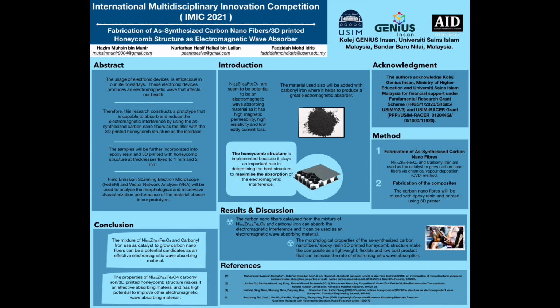So for the method part, it is divided into two phases. The first one is fabrication of synthesized carbon nanofibers. Nickel zinc ferrite nanopowder will be produced by using high energy ball milling apparatus. The milled powders then will be sintered at 900 degrees Celsius for 10 hours. The nickel zinc ferrite will be further mixed with carbonyl iron and used as catalyst to grow carbon nanofibers. An ethanol solution is used as the carbon source to grow the carbon nanofibers by chemical vapor deposition method.